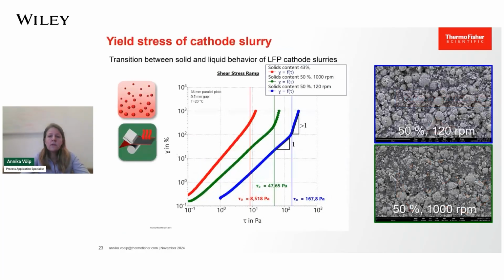The yield stress of a suspension is the minimum stress that needs to be applied onto it to make it flow. When the sample is exposed to increased shear stress, the measured deformation increases linearly with a slope of 1 in a log-log plot until the yield stress is reached, and then the sample starts to deform disproportionately.